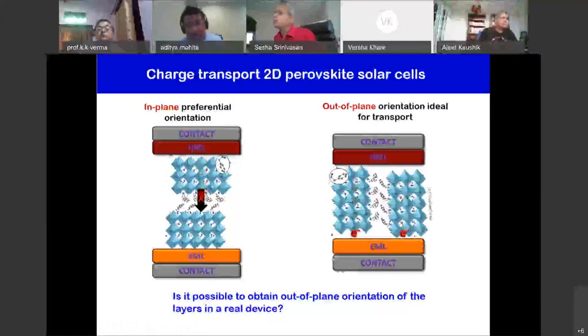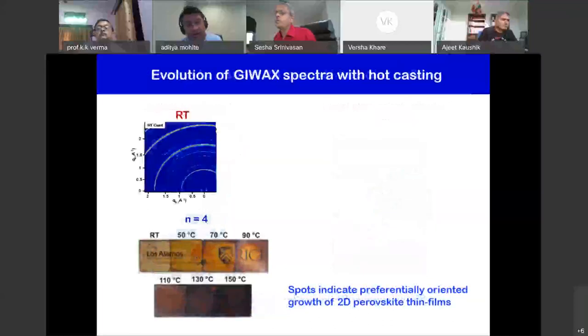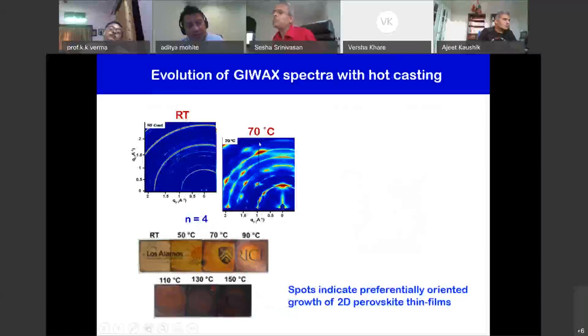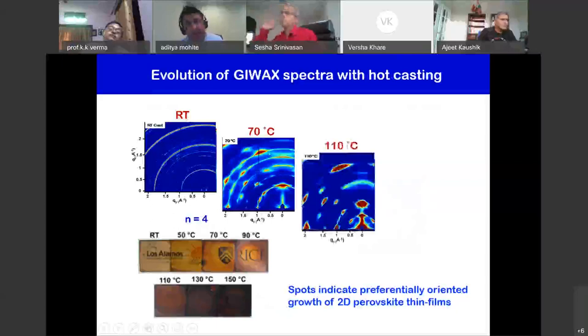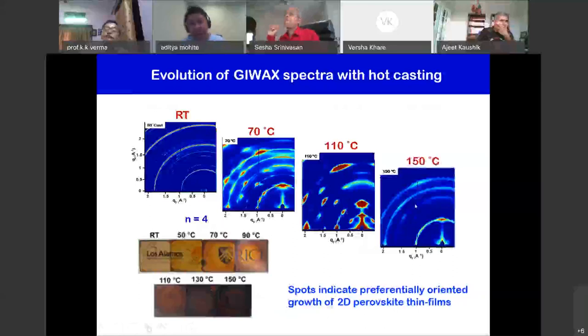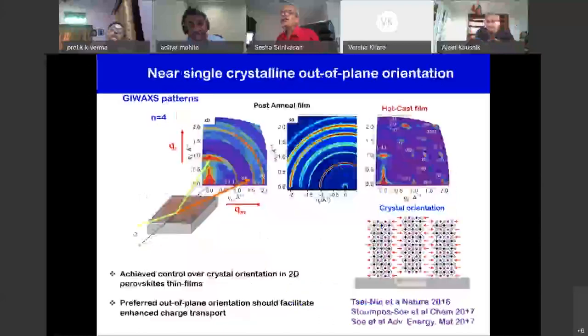And so we applied this hot casting technique to try this. And so here's a two-dimensional X-ray diffraction spectrum, where this is at room temperature. But as you increase your substrate temperature, what you're able to see is that this spectrum turns into spots. Okay. If you keep doing this, you start seeing these very nice spots. If you go too high in temperature, of course, then you lose crystallinity again. And so whenever you see these spots in your diffraction spectrum, just like Anshul was saying, showing some of these diffraction patterns, you know that you are looking at a near single crystalline material, or something which is very well oriented. And so what we did was we did the hard work of sort of...